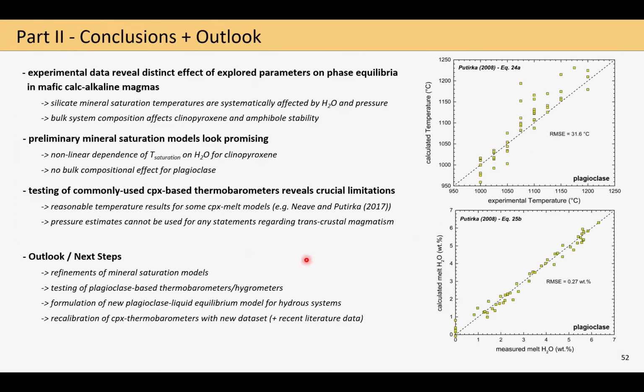And with this, we've now reached the second part of my talk, and I hope I could show you how we can use IHPVs to run a systematic study, for example, on the effect of pressure, water content and bulk composition on phase equilibria in mafic calc-alkaline magmas. And that we can also use this data to try to predict phase equilibria by formulating some mineral saturation models. The data sets can also be used to test commonly used CPX-based thermobarometers for their general performance, where we saw that temperatures are occasionally reproduced and the results are reasonable, while pressures are, in fact, certainly not.